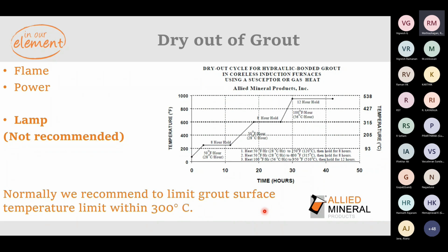So we recommend to follow the cycle recommended by the refractory supplier with the help of a thermocouple. This will help to remove the complete moisture from the system in a slow phase. The dry out cycle can be designed based upon the size of the furnace and the amount of grout material consumed. Normal recommendation is to raise the temperature till 300 degrees Celsius.